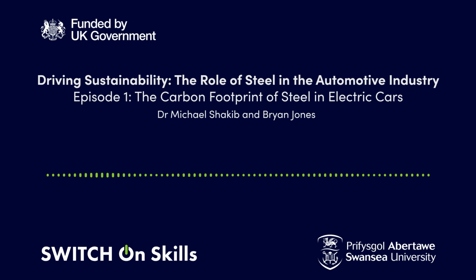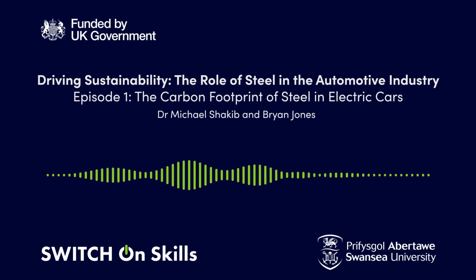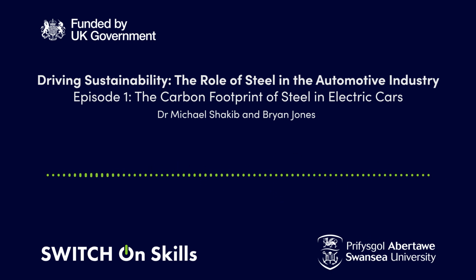So in this future steel vehicle project for a battery electric vehicle, the amount of mild steel dropped significantly down to 2.6%. High strength low alloy steels of 450 megapascals yield stress, and bake hardening steels with strengths of 340 to 400 megapascals for outer panels of the vehicle, accounted for 32.7% of the vehicle architecture. The remaining products used were a combination of hot-formed boron steels, as I mentioned earlier, 11% of such products with a tensile strength of 1500 megapascals, together with dual phase steels of tensile strength from 500 to 1000 megapascals, TRIP steels, which contain typically 1.5% manganese, and also a limited amount of complex phase steels as well. So by doing that, this is felt to be the optimized use of steel products for the future.